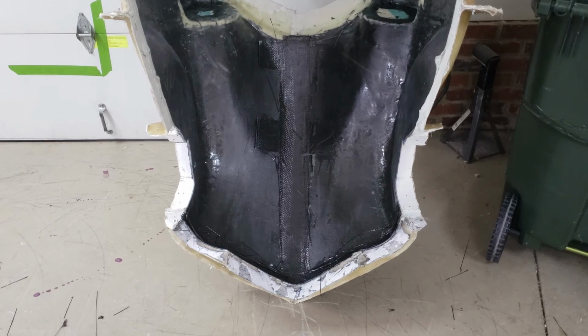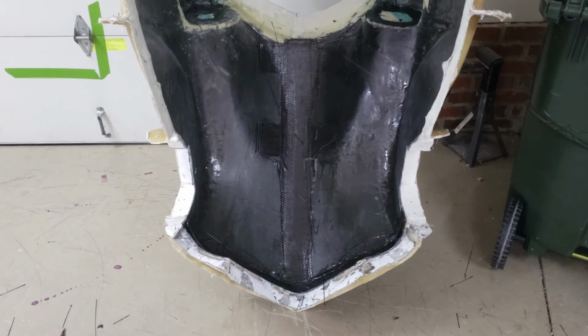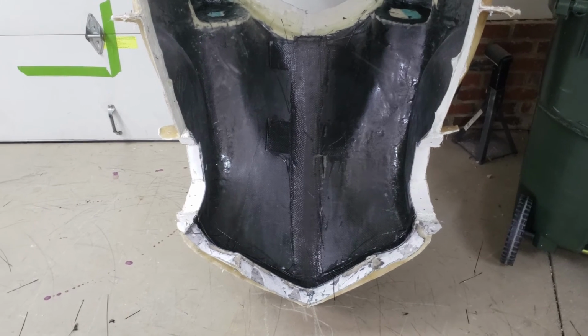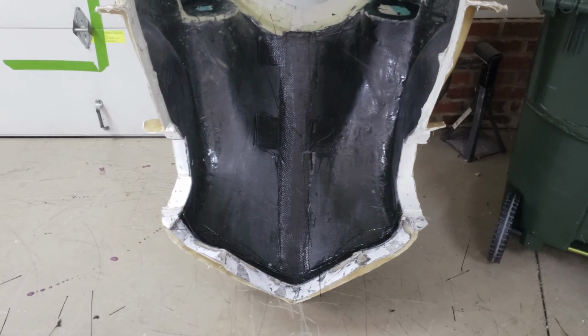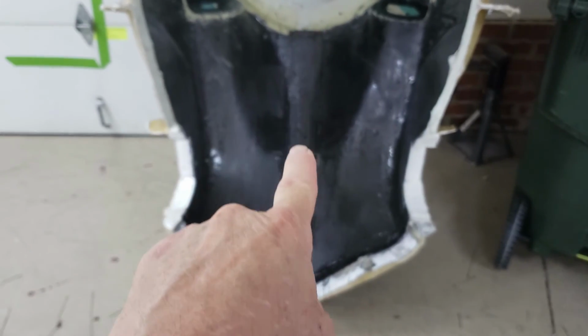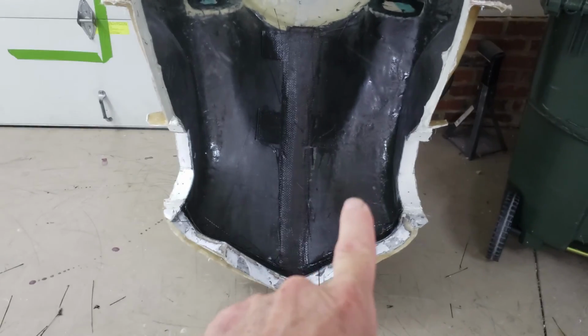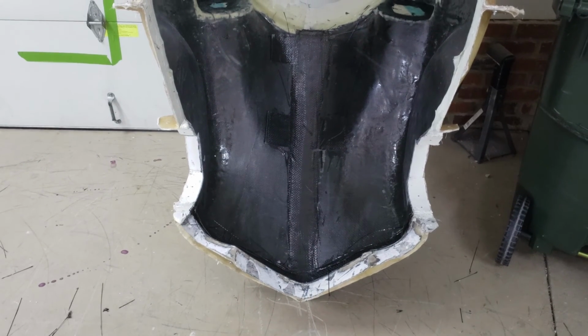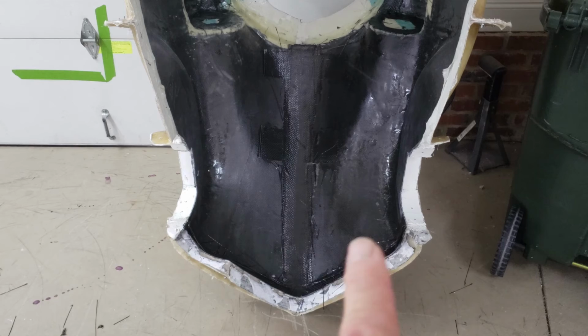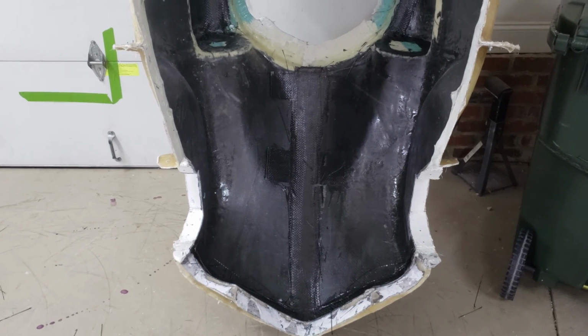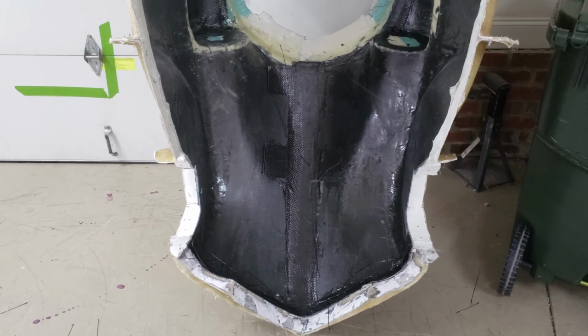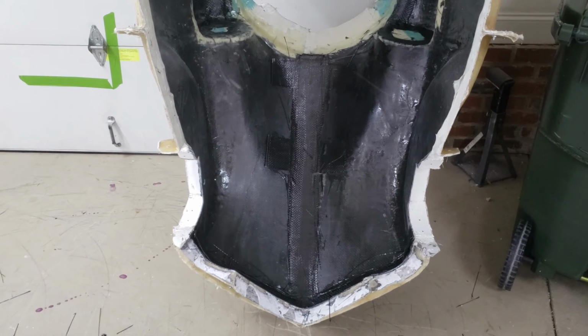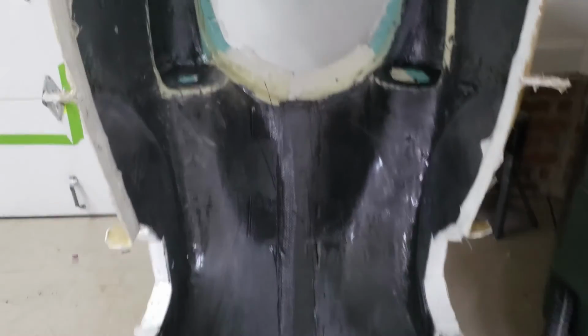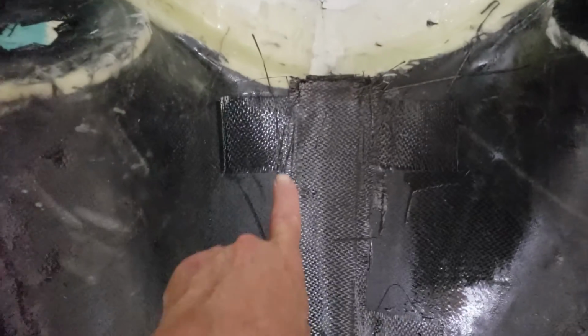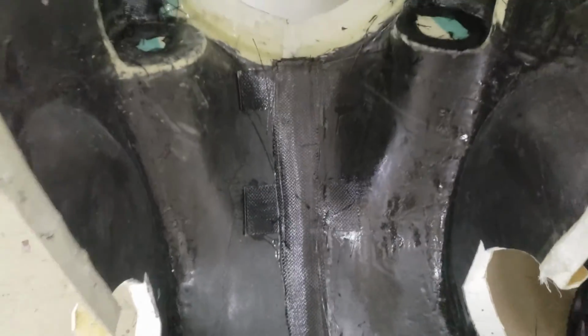I finished the patch. Started out with some fairing compound that I made from epoxy resin and Cabosil. It's a filler to make a paste to go down in the gap between these 2 areas, right down in here. That goes between this area and that way. And made sure it had a nice smooth transition from one side to the other. And then put down 4 layers of 6-ounce carbon fiber right down the middle. Got a nice bonding on that. I also put in a couple of little stretchers here. If you can see this one that goes across here, the one that goes across there, just to make sure it never pulls apart.